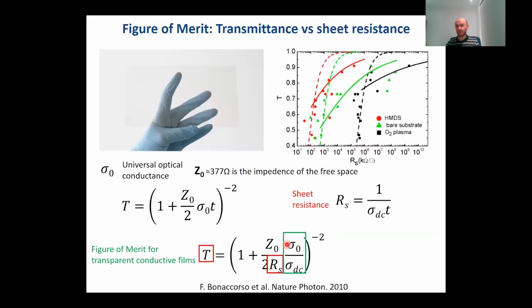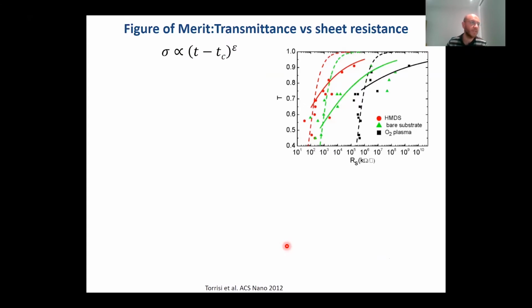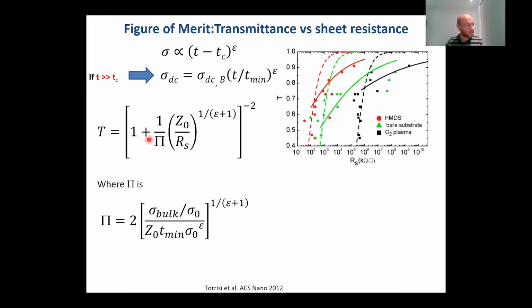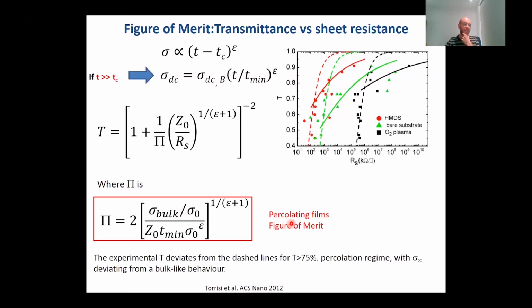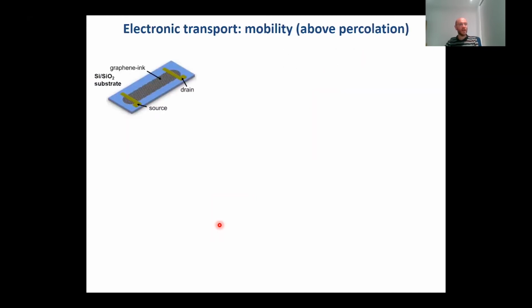Now, normally these two parameters are constant for a material, but because the conductivity, as I told you, deviates from standard bulk-like behavior, we can see this experimentally. These dashed lines would be what a graphene single sheet would look like, and that's what happens with our flakes. So the conductivity, we know that above the percolation threshold, when T is much larger than TC, actually corresponds to this equation here, where the bulk conductivity is modulated by the ratio between the thickness and the minimum thickness. So we can also modulate the transmittance with a new figure of merit that we call the percolating thin films figure of merit, where this is actually described. By doing this, essentially, we could optimize our printed devices.